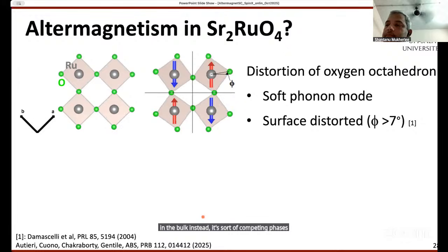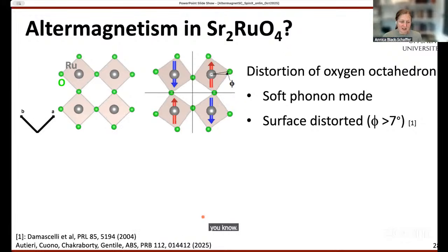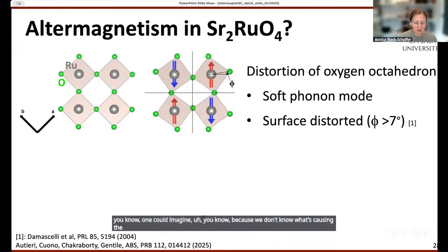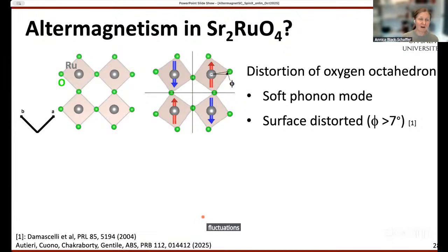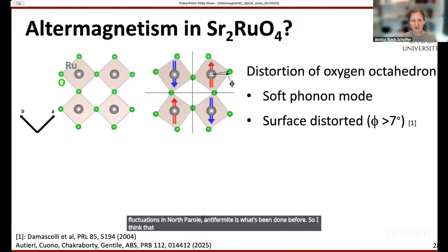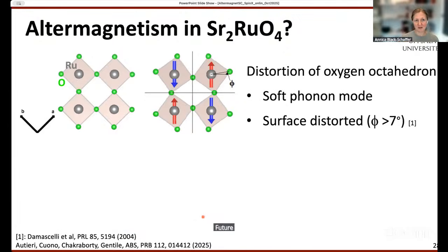Of course, one could imagine, because we don't know what's causing the pairing in strontium ruthenate, that if it is spin fluctuations driving it and it's close to an altermagnet, then one should do a spin fluctuation calculation with the altermagnet fluctuations, not ferro or antiferromagnetic ones, which is what's been done before. So I think that is an interesting future direction to consider.